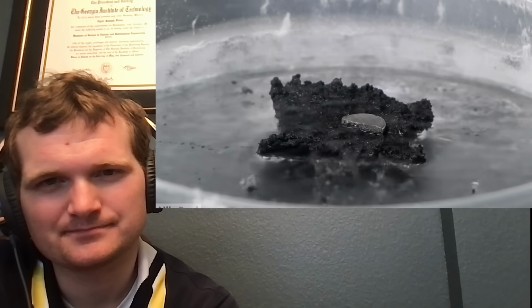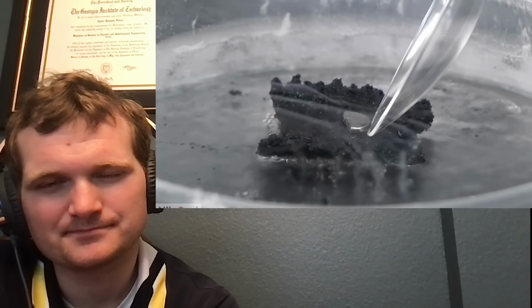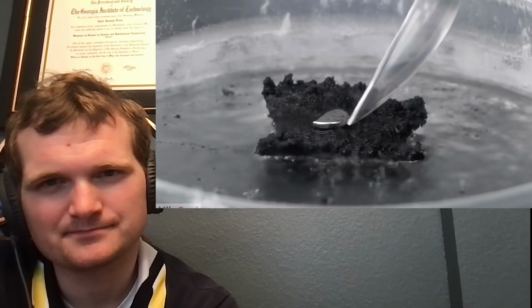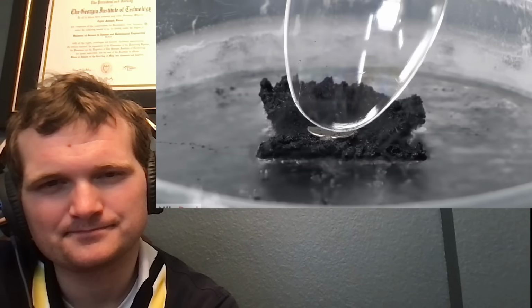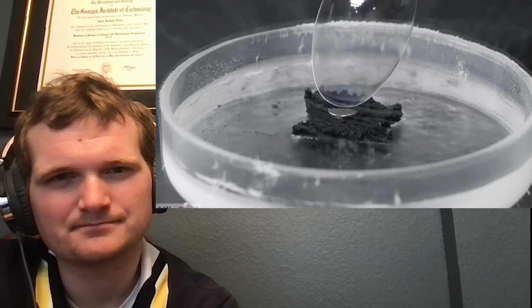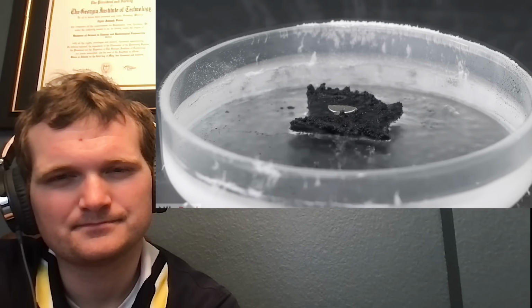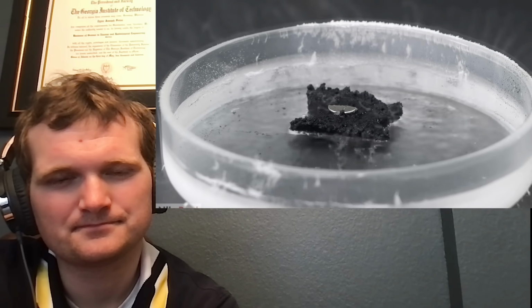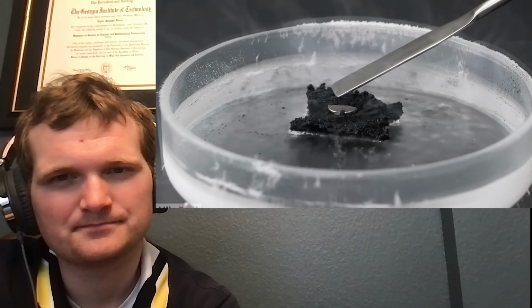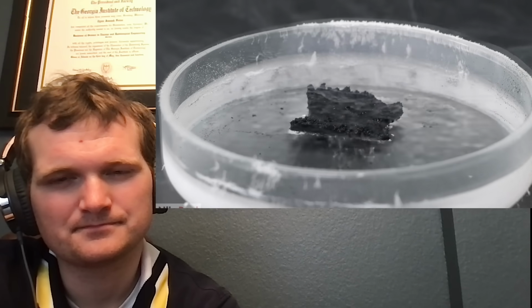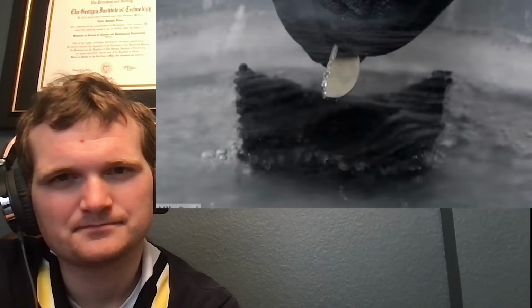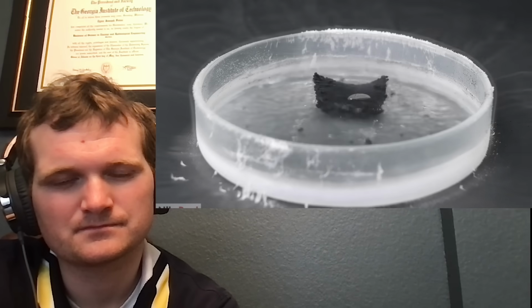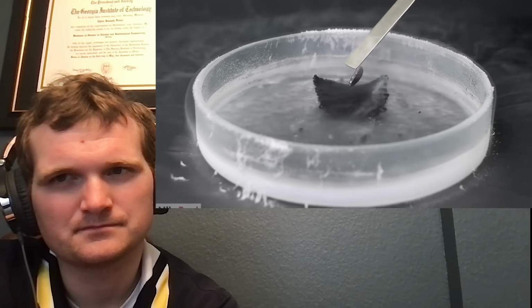The first problem was that it was still too light and fluffy, and there wasn't actually very much here. The second, and probably bigger issue though, was that I don't think it was oxygenated enough. YBCO always has the same ratio between the yttrium, barium, and copper, but it's able to vary between 6 and 7 oxygens. However, it's only able to superconduct in the 7 form, and what I had probably still contained a lot of the 6 form.